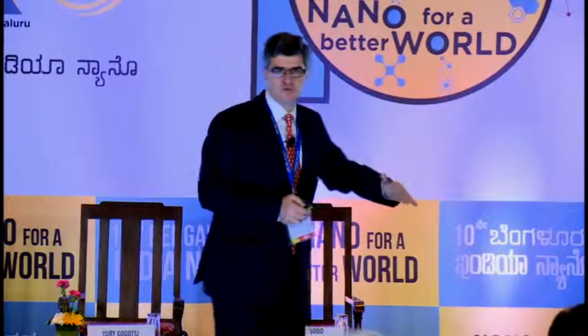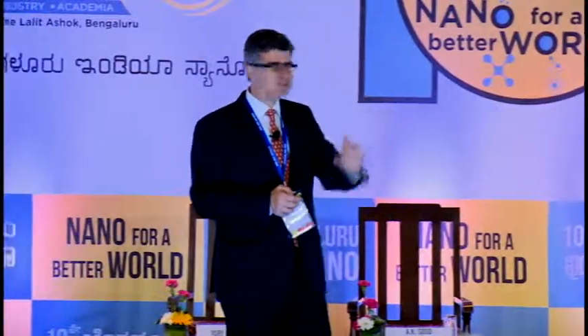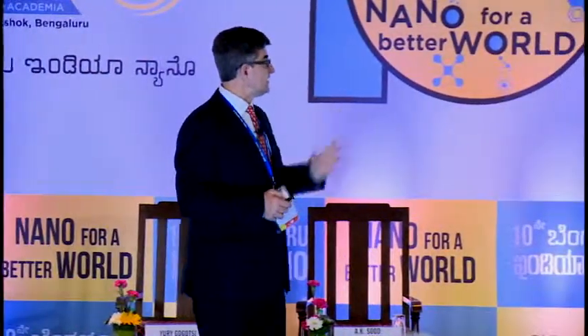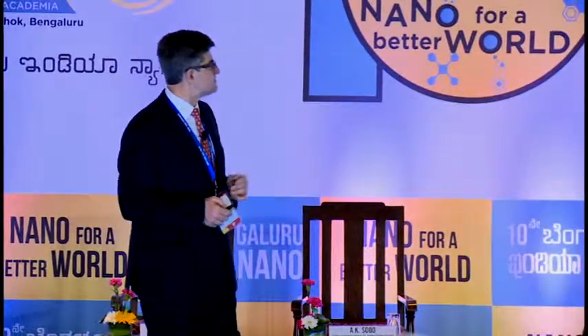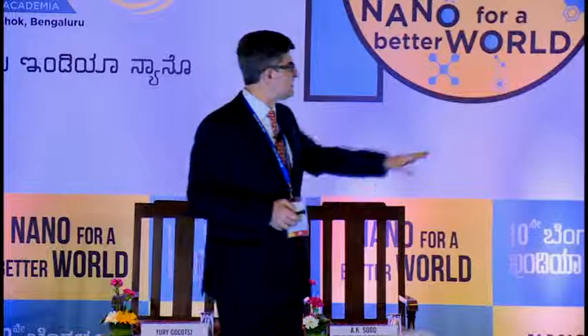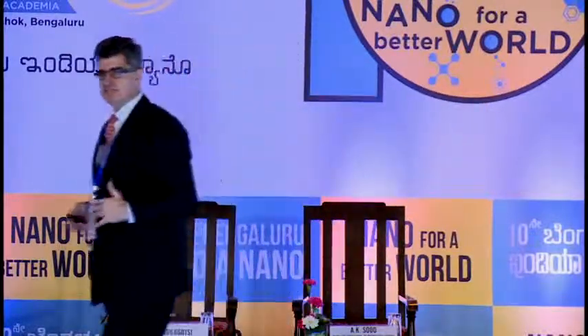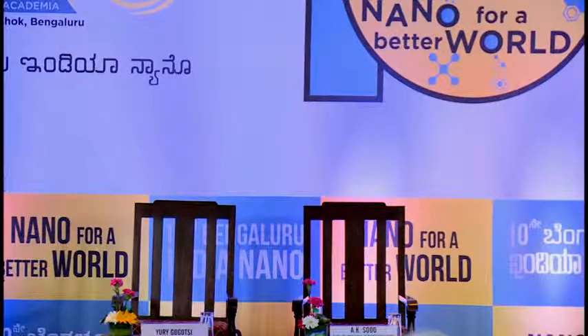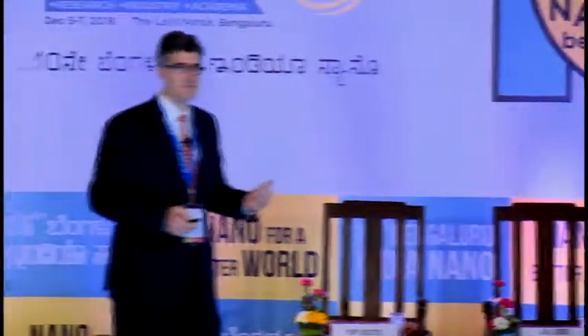And actually, we can load quite significant layers of the materials here. And we can make transparent conducting films. And actually, this is a transparent microsupercapacitor. And you can see from the bar on the right side, it actually has significantly higher capacitance per volume compared to, say, conducting polymers or graphene carbon nanotube films here.